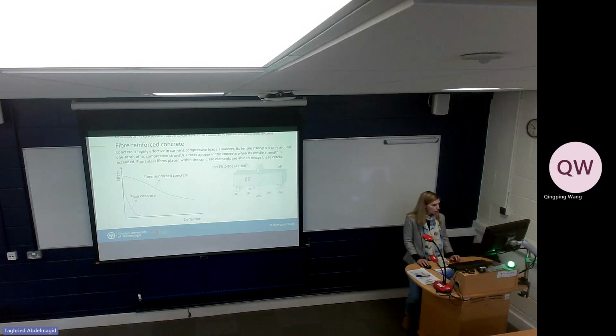First of all, I will show you the diagram from the material tests that are used to check the efficiency of the fibers in concrete. When we have small beams with a notch and we do not add the fibers, the beam actually breaks. So the concrete without the fibers is completely brittle. It has a very high compression strength, but the tensile strength is only 1/10 of the compression strength, so it's nothing. When some tensile forces appear, the concrete just cracks, and that's all. That's why adding the fibers is very useful.